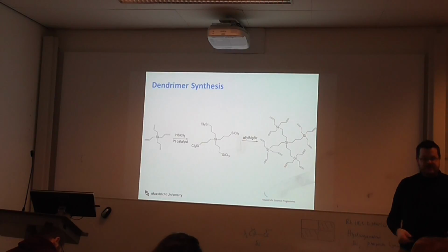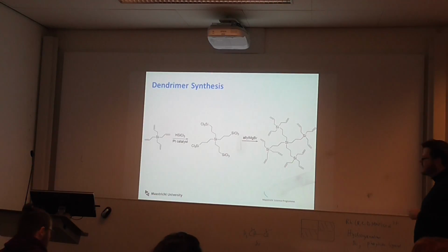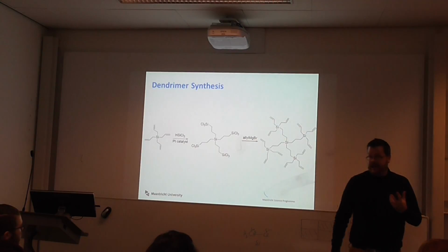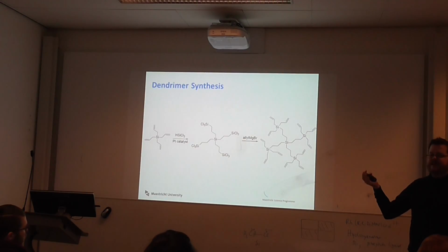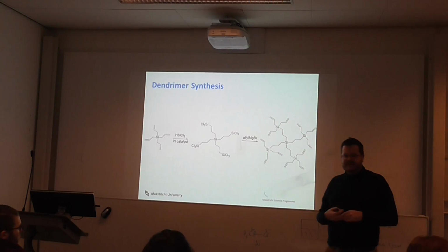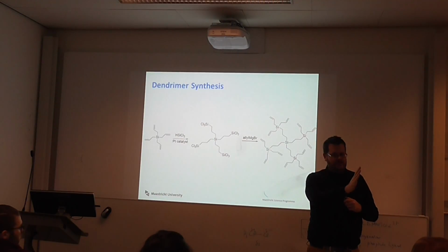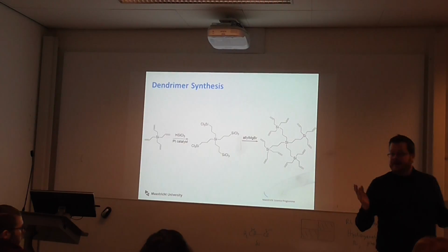And why would you want to do that? You'd want to do that because it's a useful material in bridging the gap between homogeneous and heterogeneous catalysis, because you can separate it by ultrafiltration methods. And that was really why people were making dendrimers in the 1990s in particular, because they thought it would solve this problem of removing spent catalyst or catalyst species from the product by using ultrafiltration methods. In other words, very fine membranes that would selectively allow the desired product to pass through but retain the catalyst behind. It wasn't that successful in the end, in my opinion.